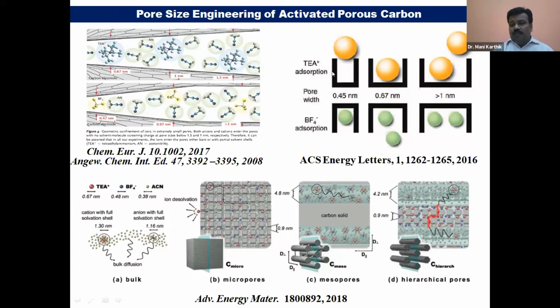If the pore has a very narrow mouth, these ions are not able to penetrate inside. If you have a wide one, it can really go. If you have a very wide one, there is too much adsorption. So if you see this, another challenge is tetraethyl ammonium has a different size here, a different size here. This is the bigger size, this is the smaller size. So now that is a challenging task for material scientists.